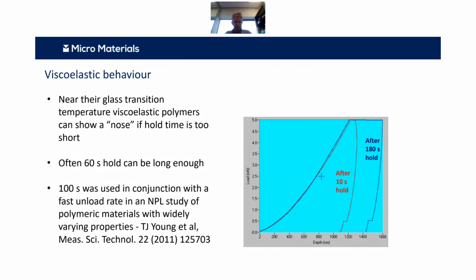So this is actually not a biomaterial. This is a polyester. And we've just got a couple of examples there where the only difference, indents at different positions, is the difference in the amount of hold at peak load before we're unloading. And in the red curve, you can see this so-called nose or bow during unloading. If you try and apply standard elastic unloading analysis to this, you don't get a sensible elastic modulus measurement at all. However, if you apply the same analysis after a sufficient hold period, then you can get reliable numbers.